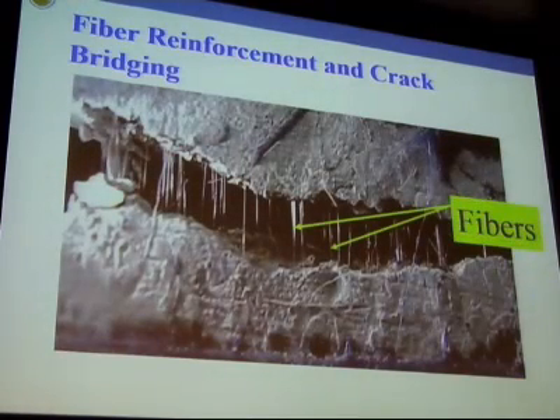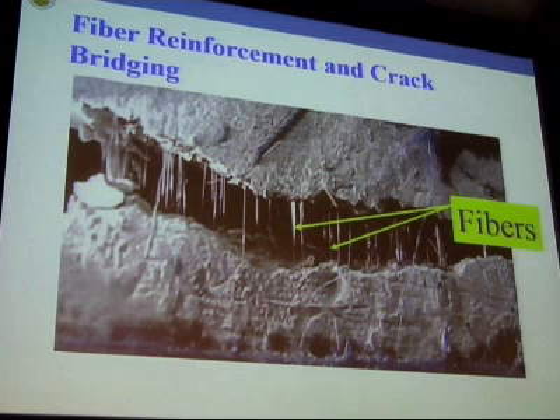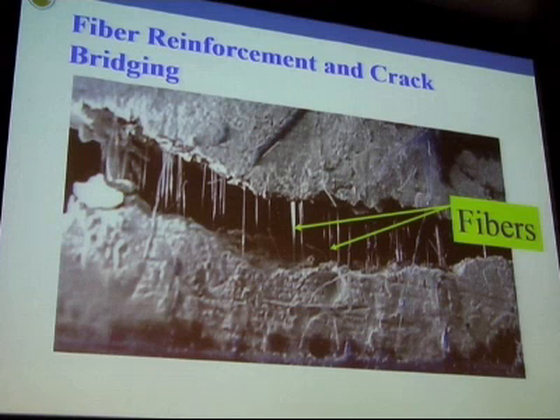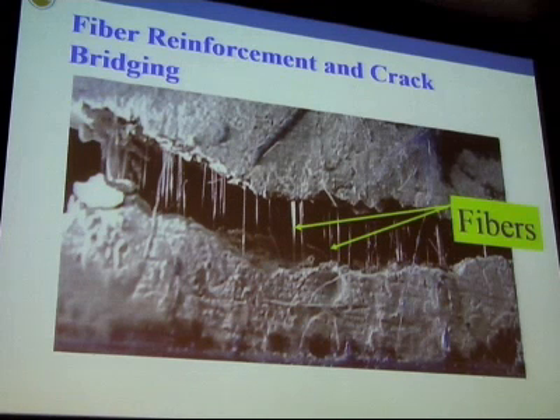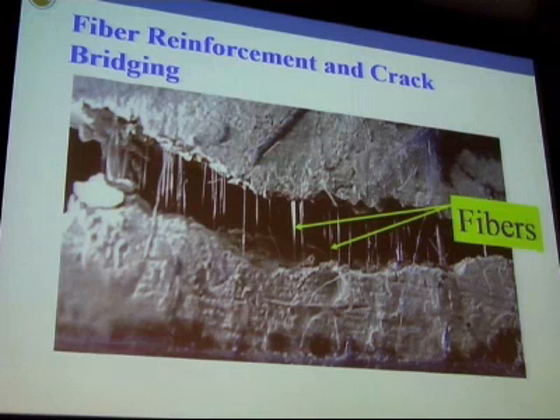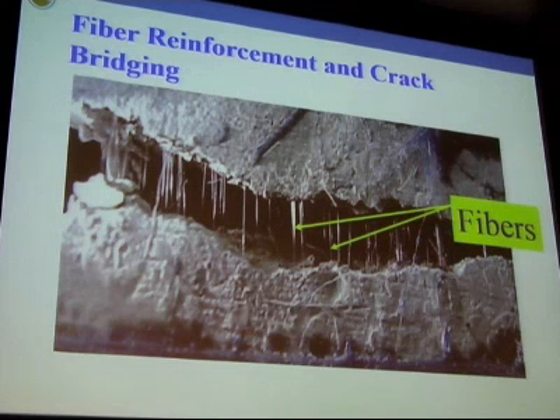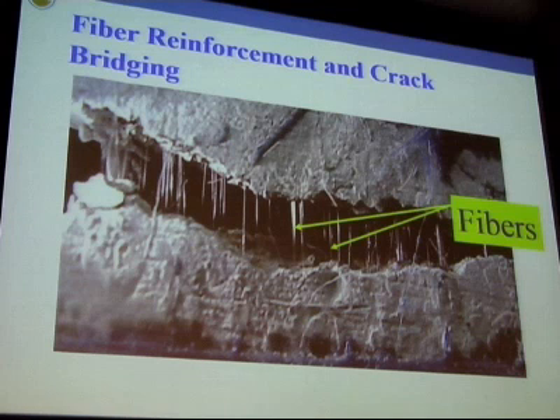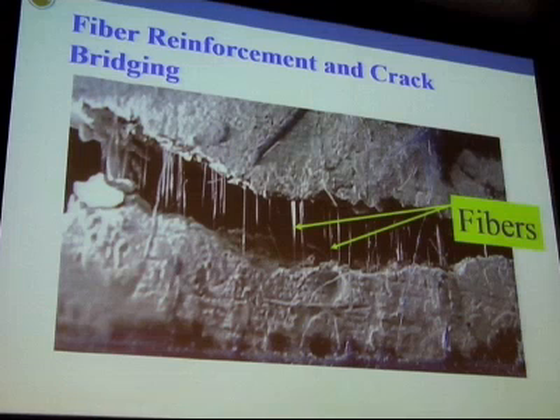The crux of the matter, in fact, the primary mechanism by which you can make a material absorb a lot more energy, is the fiber bridging effect. So basically, if you have concrete which does not have fibers, once you have a crack, this crack would have very low stress carrying capacity. The moment you have fibers in there, you essentially have a stress carrying capacity across a crack, and this is what we call a residual tensile capacity or residual compressive capacity. So you would have basically this kind of a response.